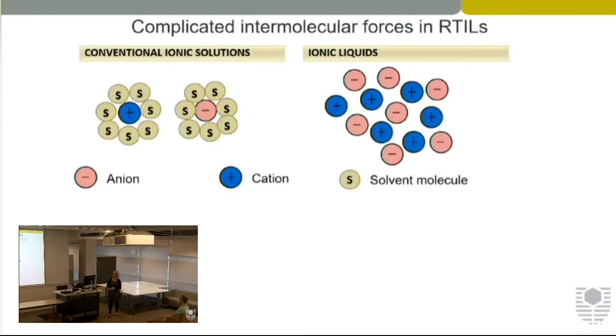So if we think about ionic liquids in terms of a solvent, and we compare them to a conventional ionic solution. So here you could just have potassium chloride dissolved in water. A conventional ionic solution would have the ions which are dissociated and surrounded by solvent molecules. Ionic liquids are quite different. They have larger ions, and as you can see, there's no solvent molecules. They are both the ions and the solvent.